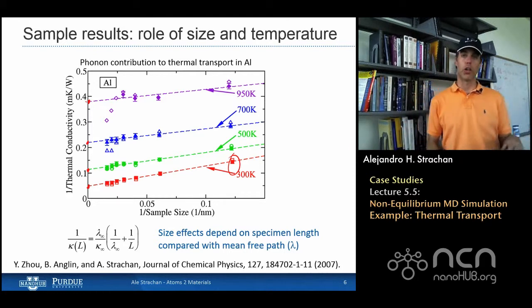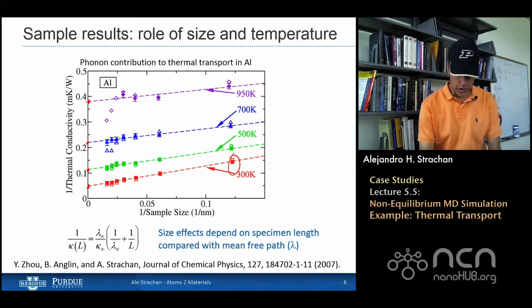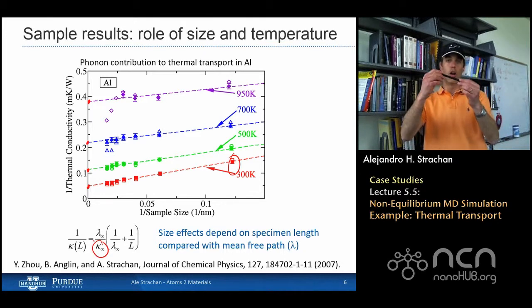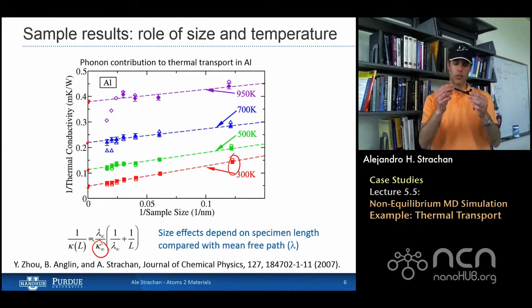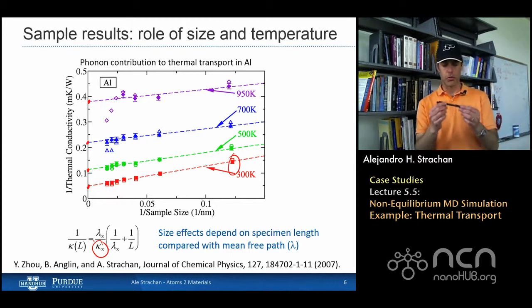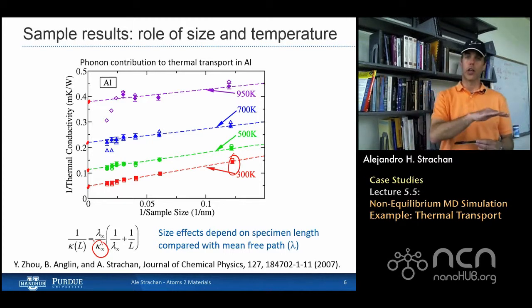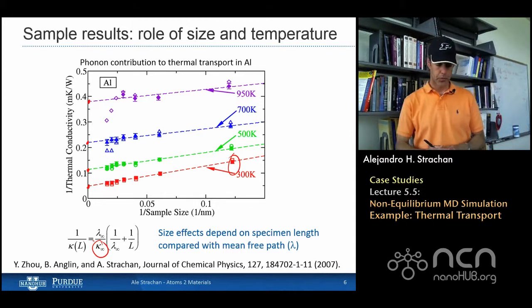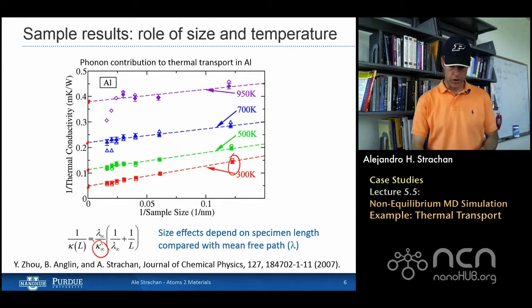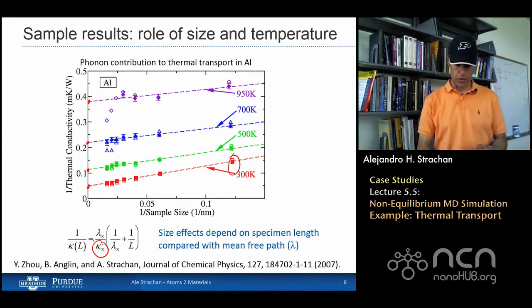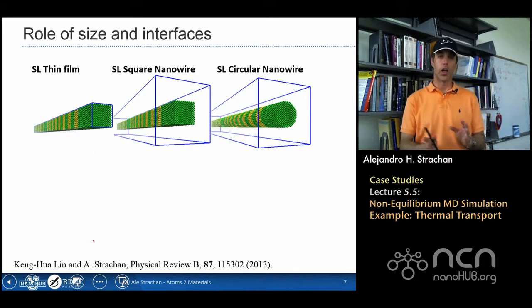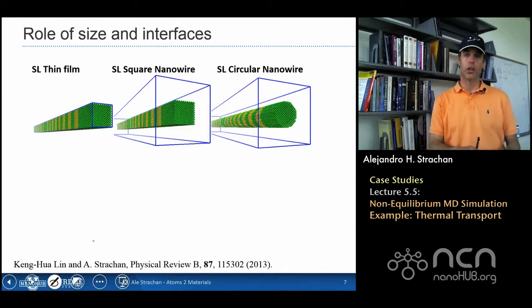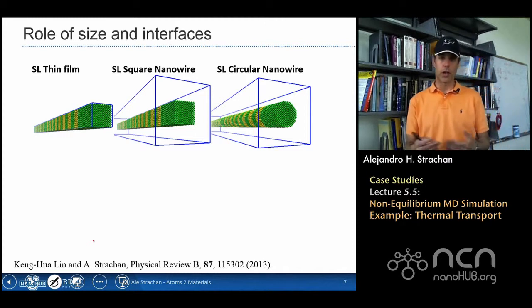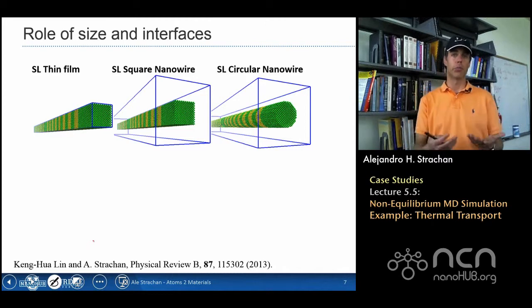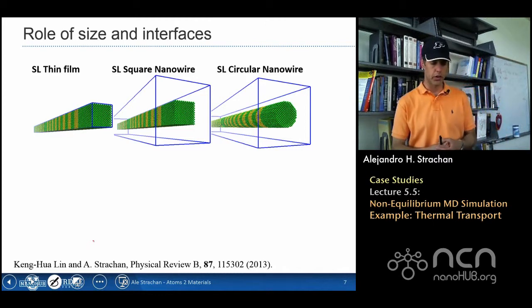And from these extrapolations, we can predict the thermal conductivity of the bulk samples, and the slope of these linear relationships tells us about the mean free path of the phonons, okay? So you can get very interesting properties out of this. Now, let me tell you a little bit about some recent results from our group that I think also exemplify the power of MD simulations in this field.